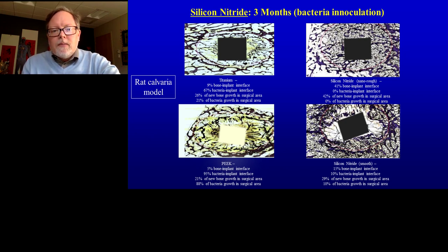So then you look at the best material, and that was the silicon nitride that had the nanoscale features, the nano rough silicon nitride. And again, no antibiotics were used in this study. These are simply the same chemistry, silicon nitride, that had those nanoscale features. We ended up with 0.